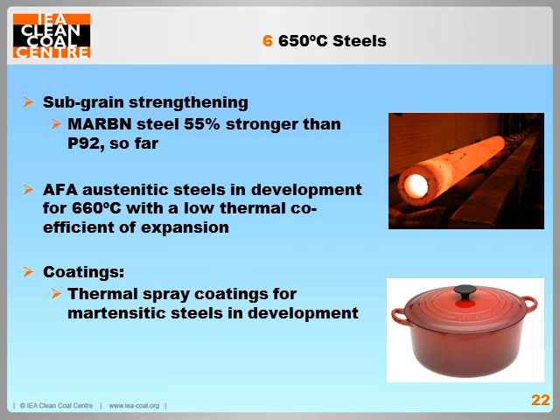Another interesting concept is sub-grain strengthening. This is where the precipitation itself is strengthened. Short-term results from projects in Japan and Europe have shown that sub-grain strengthened 12% chromium Martensitic steels are stronger than commercial state-of-the-art P92 by up to 55%.